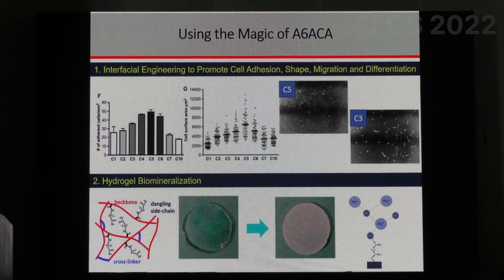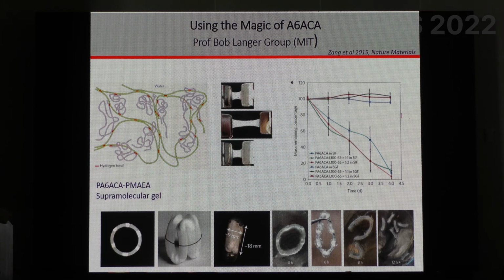We also found that with the right amount of hydrophobicity, you can biomineralize these hydrogels. So we're creating hydrogels that are very biocompatible, and you can grow hydroxyapatite or calcium phosphate in these gels, and then they become extremely biocompatible gels. And this is not work by us, but this is work by Bob Langer's group, a very, very renowned scientist in Harvard, in MIT, and what he's done is he's taken exactly the same polymer that we have, and he converted that into this exquisite material.